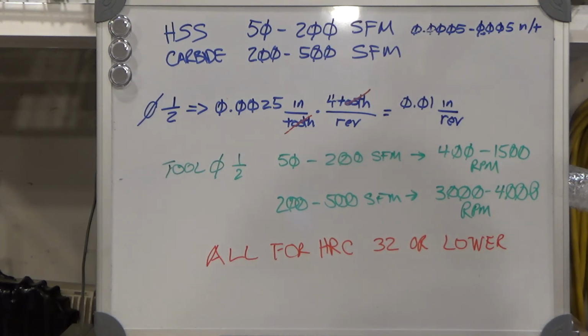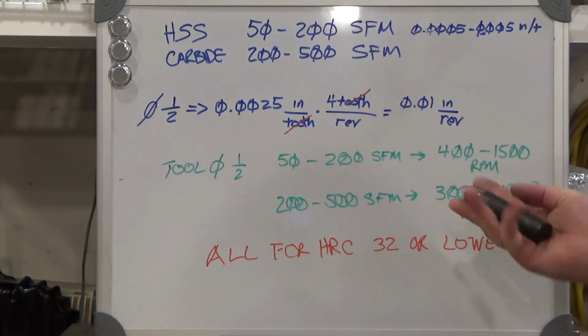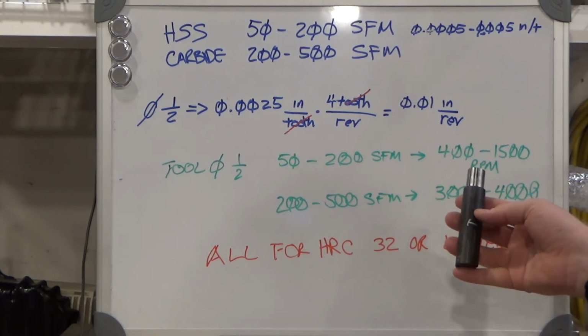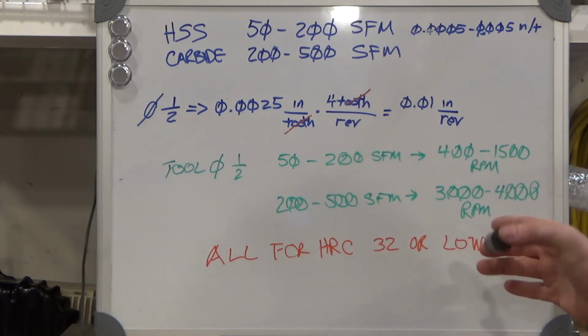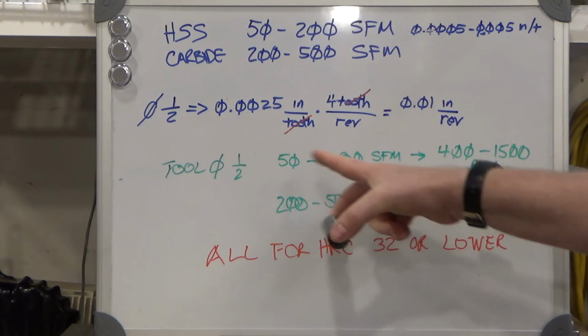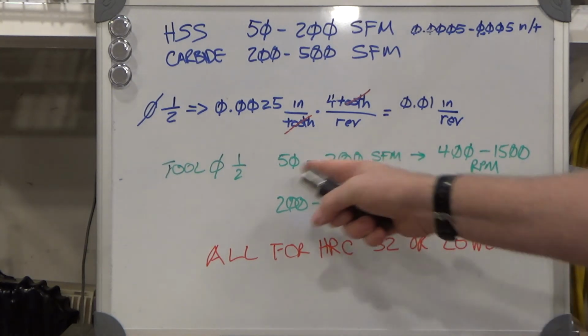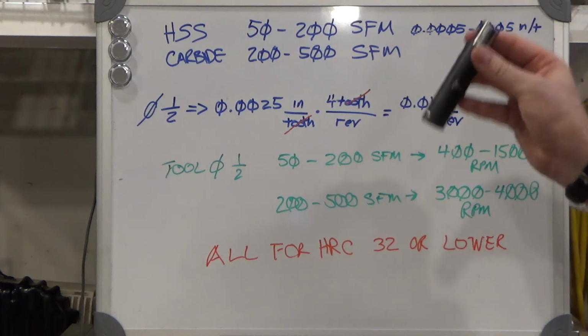So I think we should be careful as we proceed, and we will use these as guidelines and deal with that appropriately. I looked up on one site, and basically doubling of hardness means halving of surface feet per minute as a very approximate approach to this. So that would mean the heat treated and tempered part should have about half the surface feet per minute, which, if you notice the range here, fits within that range, and this is sort of at the top end of that.